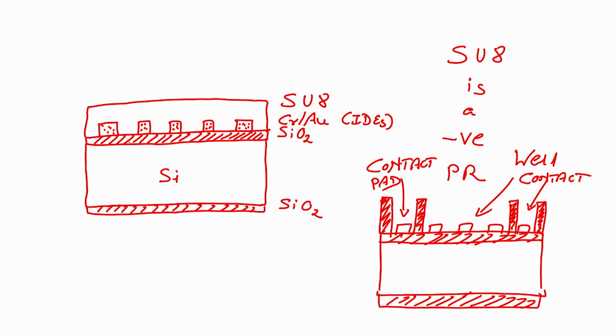Where were we? We took the oxidized silicon wafer with interdigitated electrodes, and on the interdigitated electrodes we have spin coated SU8. What is the next step? Next step is we have to pre-bake it. Now, how do you know what the temperature is for pre-bake, or for post-bake, or what the next step is when we use SU8? It is already given in the data sheet.